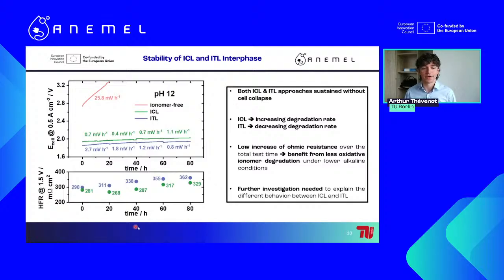Also, during this test, every 20 hours, we measured the ohmic resistance of the entire system to see how it would evolve through the stability test. And we saw only a low increase of the ohmic resistance over the total duration of the test, which is a good sign and also shows the benefit from using less oxidative ionomer, the benefit from using lower alkaline conditions that give you less oxidative ionomer degradation, as this is an issue that we can find when using highly concentrated alkaline electrolytes. And naturally, further investigation will be needed to properly explain the different behaviors between the ICL and the ITL.